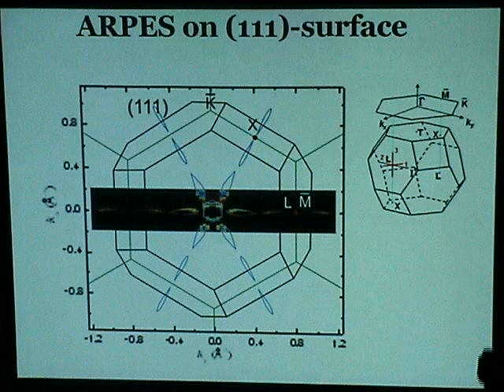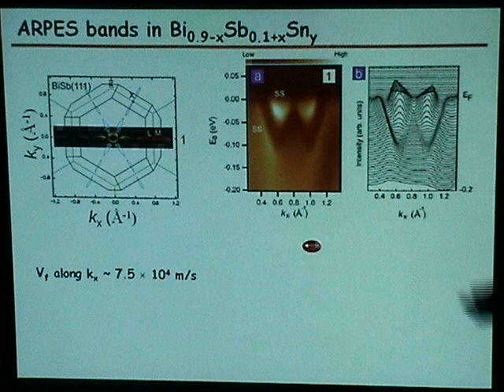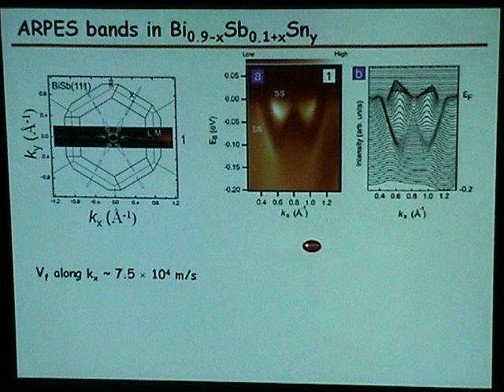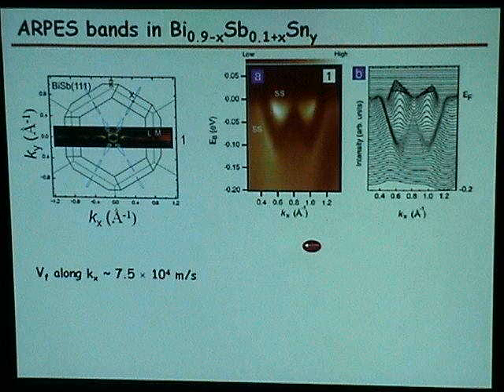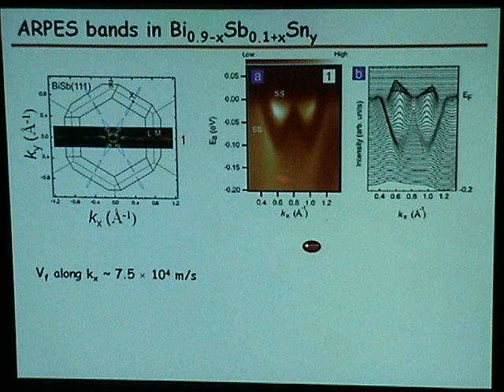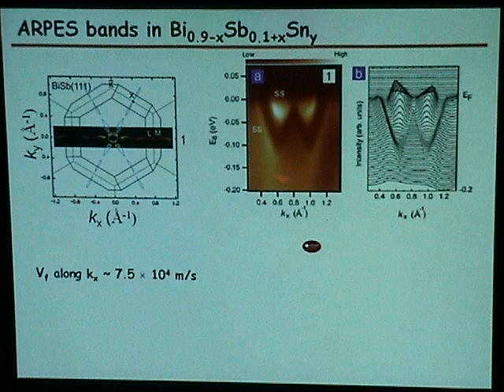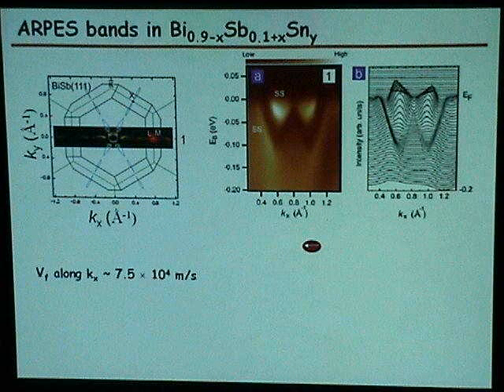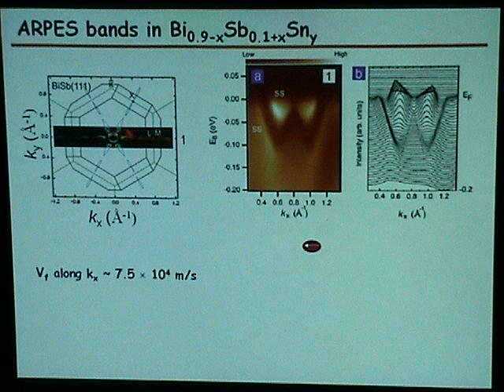Okay. So how do I know that it is a surface state? Well, I want to check if it is a surface state or a bulk state. There are systematic recipes for how to check that. So if I take this cut from gamma to M bar, I see this band, this band, this band. I see all these bands. And I also see a weak trace of a band here. One can see that it's quite rich. So this is the M point. This Fermi pocket or Fermi arc is coming from this, and that part is coming from that.